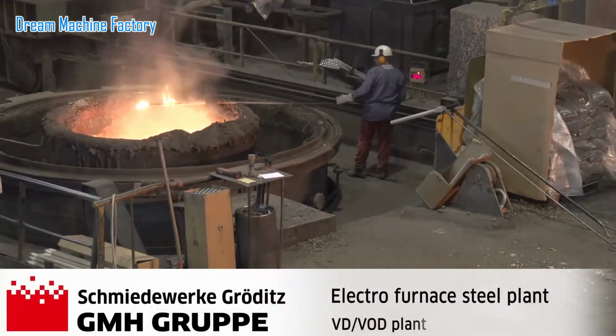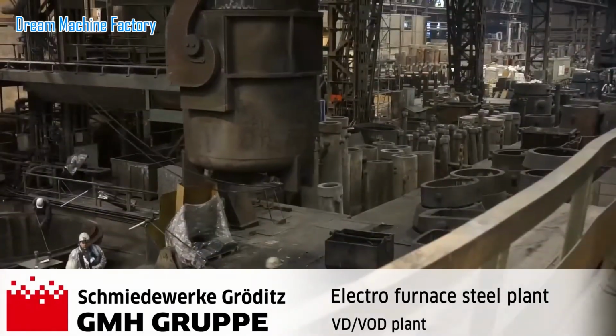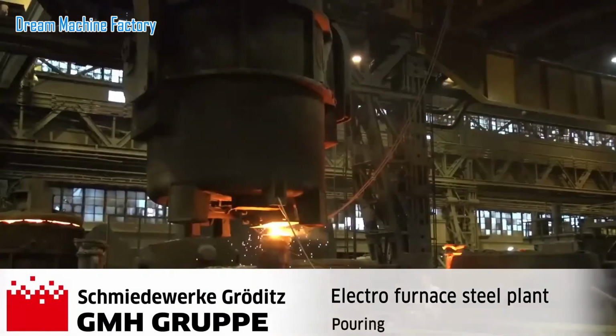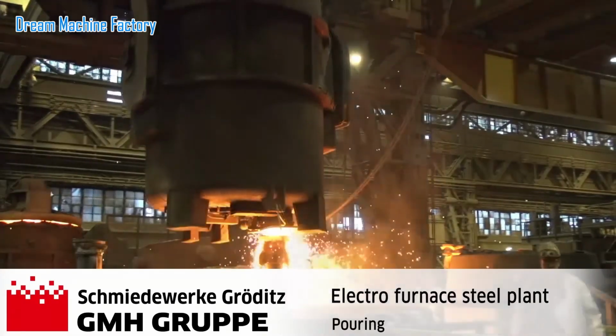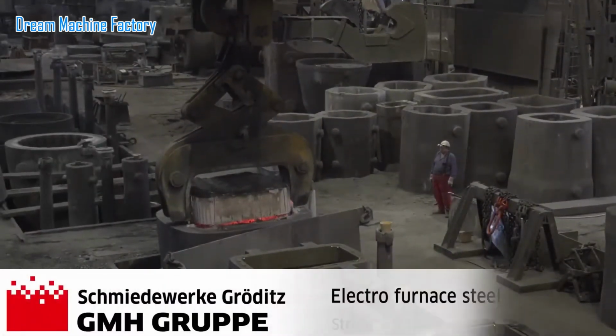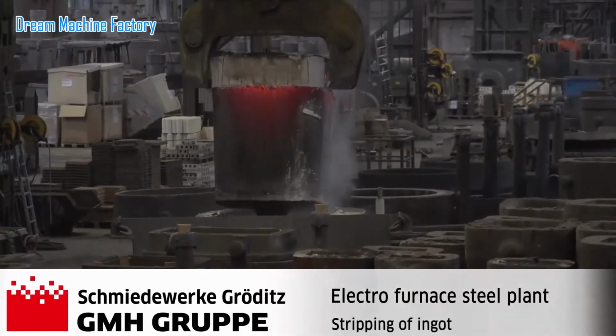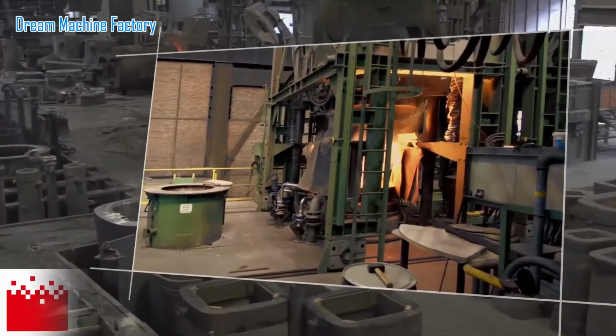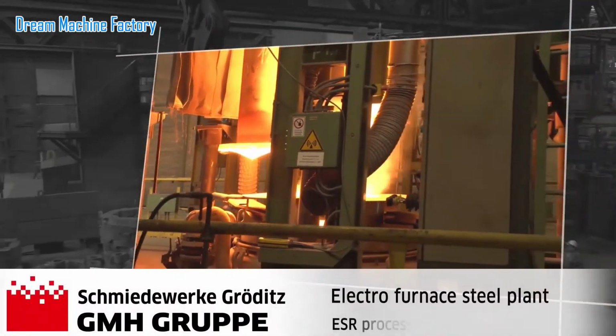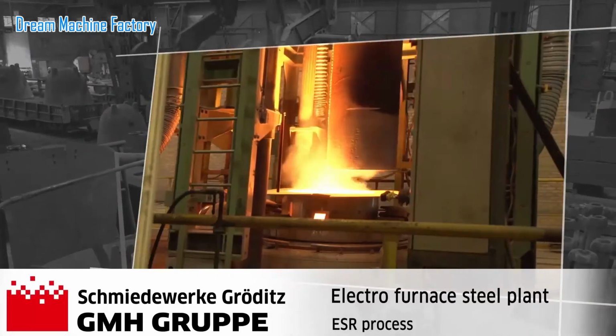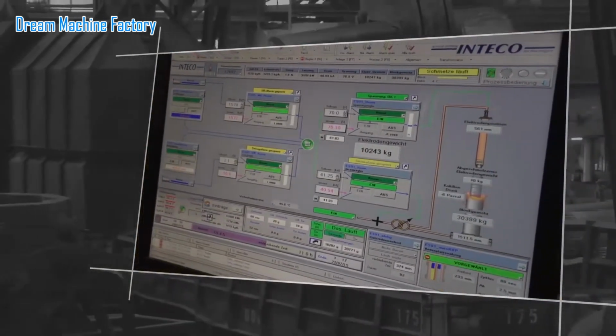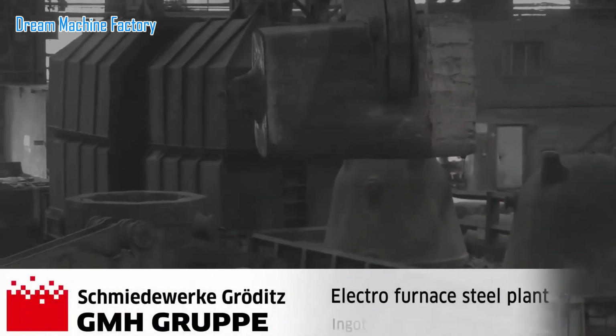The VD/VOD plant removes dissolved gases like hydrogen, nitrogen, and carbon from molten steel under vacuum. This improves purity, enhances mechanical properties, and ensures better structural integrity in critical applications. Stripping of ingot involves removing the mold from solidified steel to prepare it for further processing like ESR or forging. The ESR process remelts ingots using electroslag refining to enhance cleanliness, reduce segregation, and improve steel's microstructure and mechanical properties.